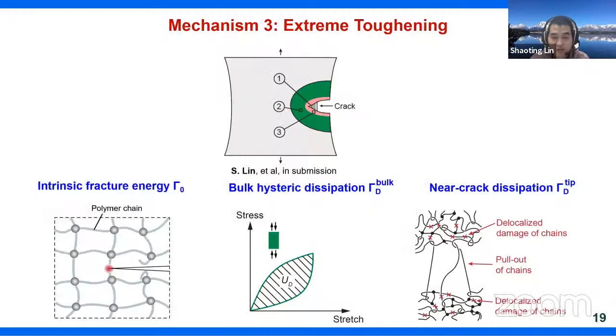Good. So let me put a few. For example, you mentioned entanglement, right? We did perform rheological calculations to characterize the different kinds of entanglement. Okay, and for crystal domains, we also did characterize, for example, use the DSC to measure crystallinity, and we also performed scattering to characterize the number density to characterize the distance between crystal domains. We also characterize the orientation of crystal domains.